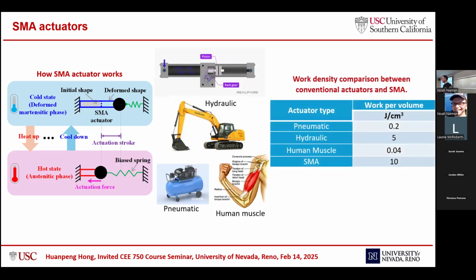So here's the work density comparison between the conventional actuators and shape memory alloy. For pneumatic actuator, it has really low work, around 0.2, hydraulic 5, human muscle 0.04, and for shape memory alloy, it can be up to 10. So it's around twice that of the hydraulic actuator.